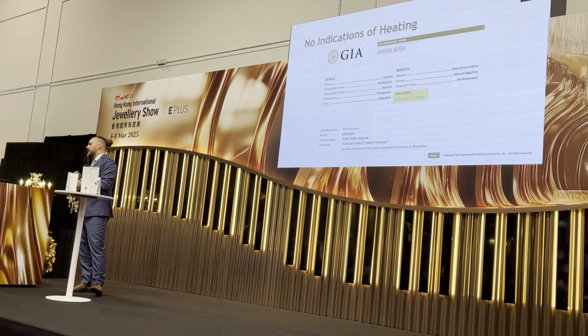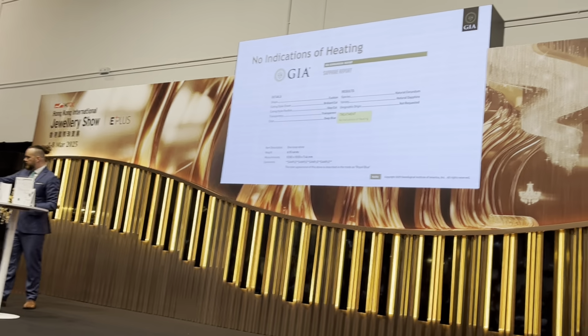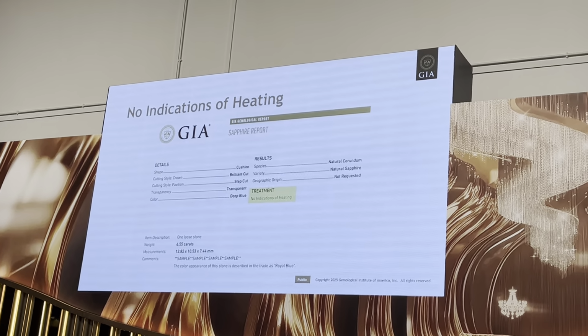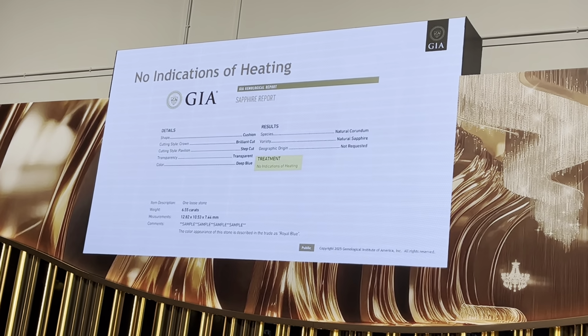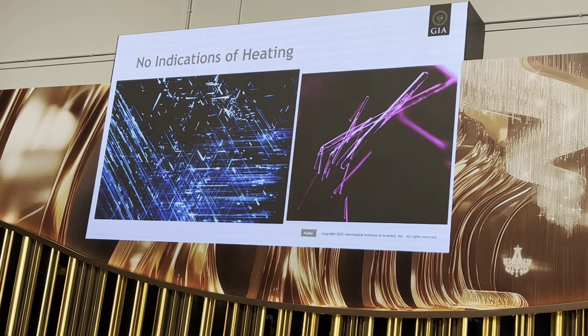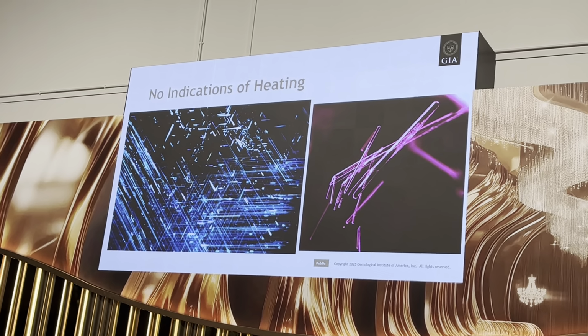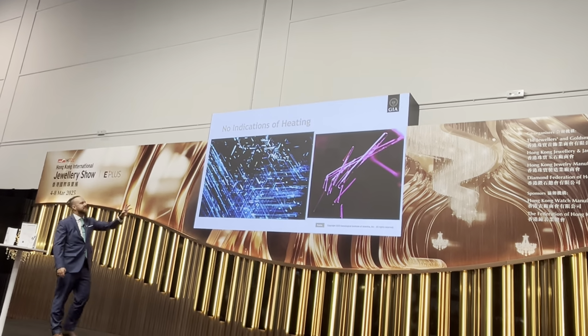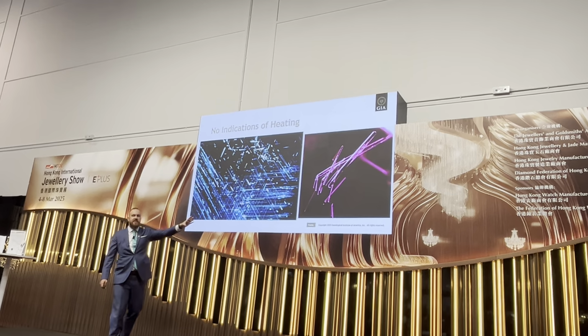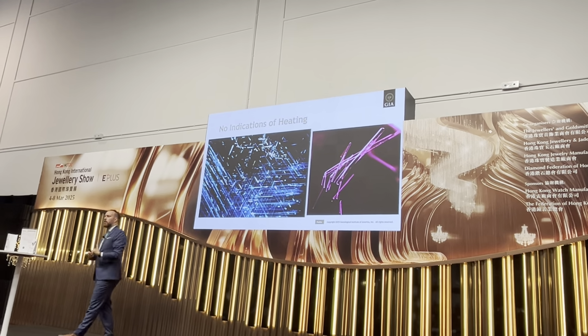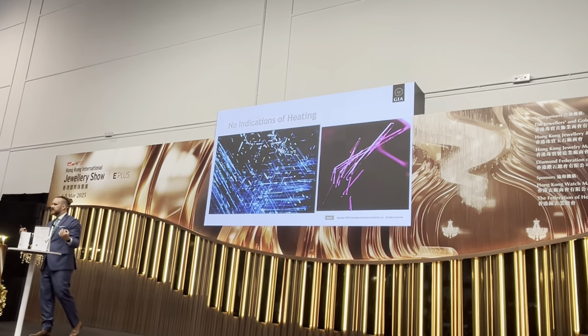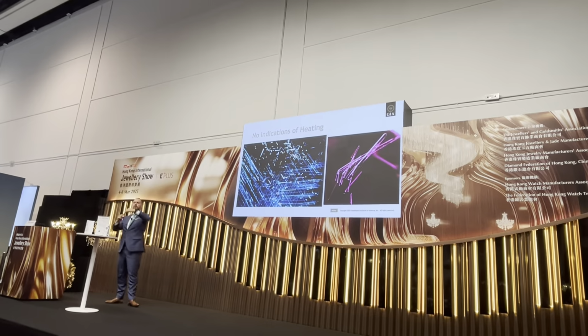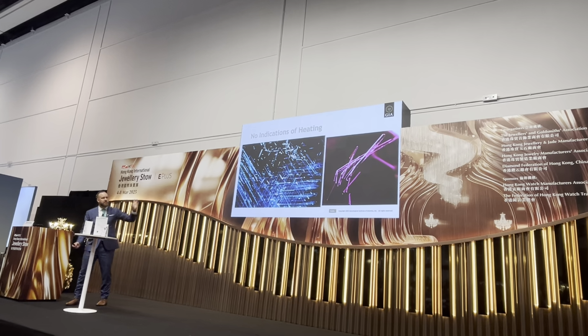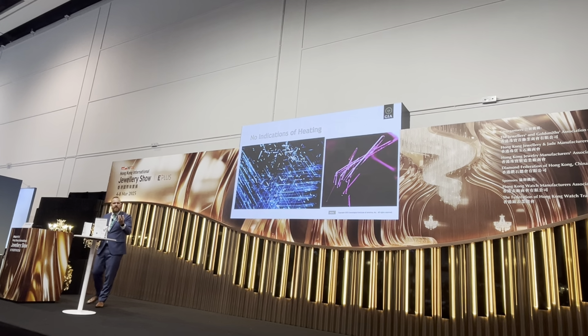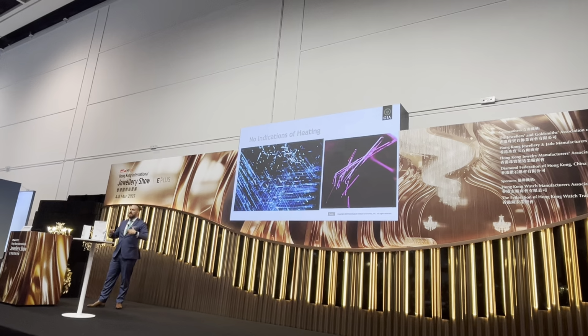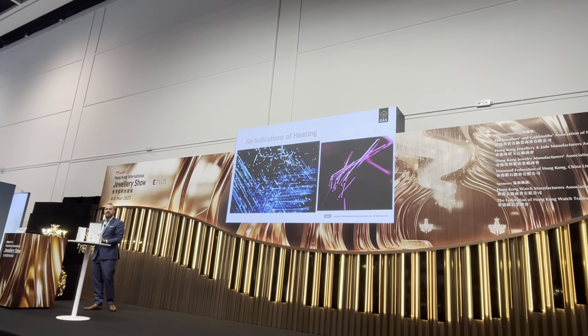Now, the first case we have to discuss is obviously an untreated stone. An untreated stone will have that listed under treatment where it says no indications of heating. Now, how do we detect that? That is mostly based on the fact that the inclusions, the impurities in the stone, for example, the crystals that we see there, or those needles, are completely unaltered. They are in a pristine state. You can see that those needles are beautifully long, elongated. Those crystals have a very nice outline, transparent appearance, completely pristine. They have not been altered by any process at high heat.